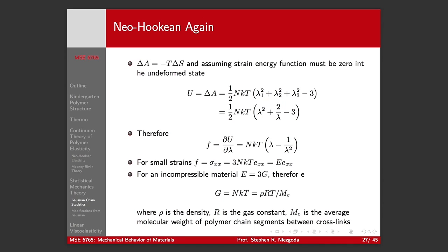So, right, assuming the strain energy function is zero in the undeformed state, and going back to our definition for the Helmholtz free energy, we have our strain energy is given by our change in the Helmholtz free energy, right, which is given here. We take our derivatives. We end up back here.